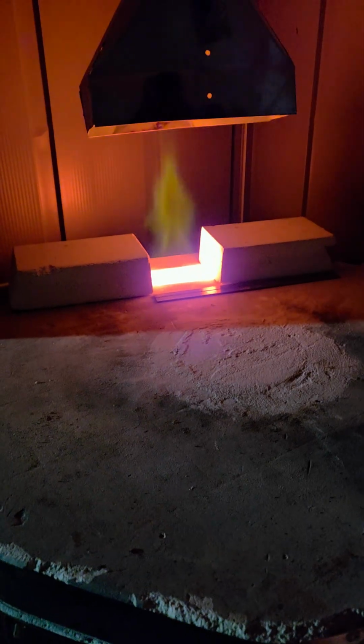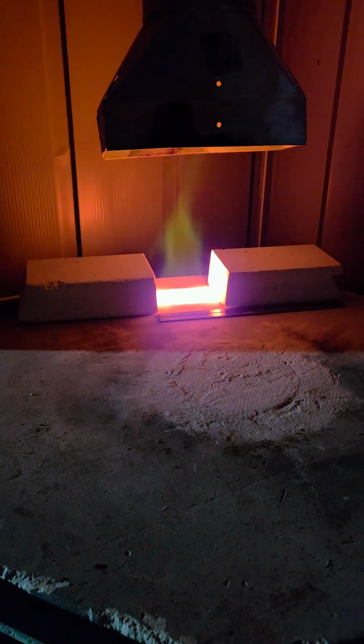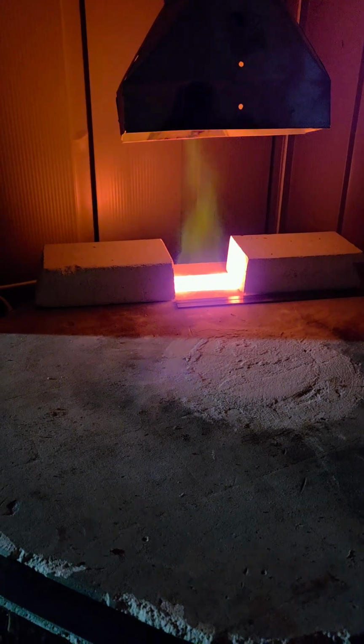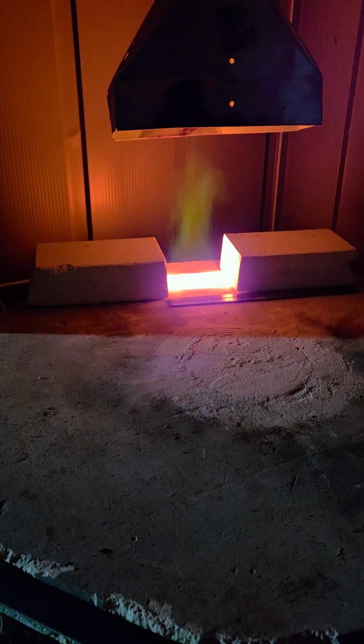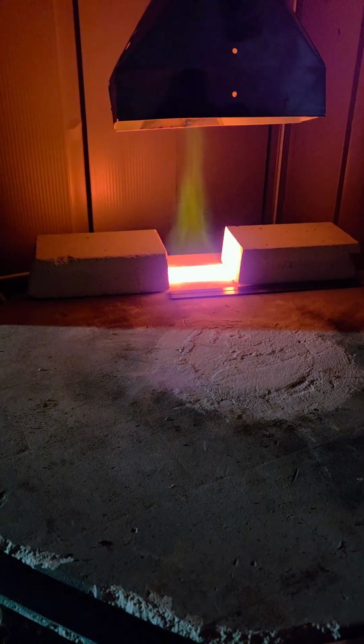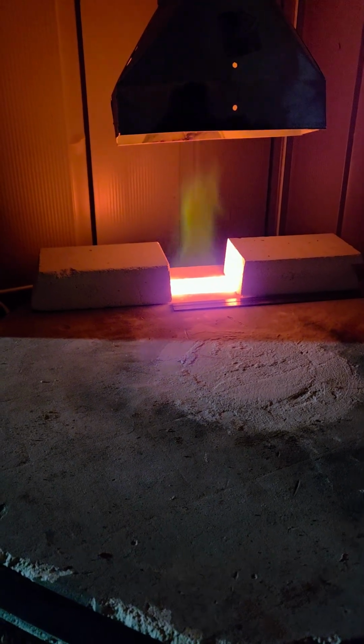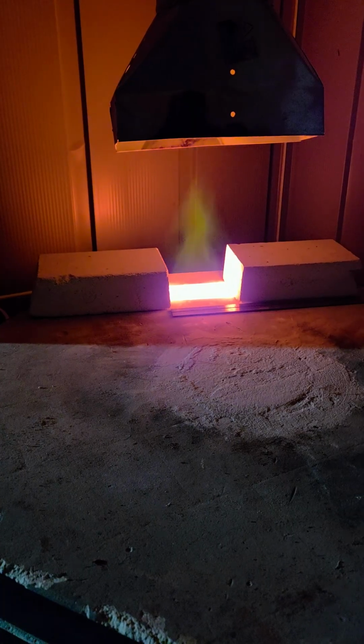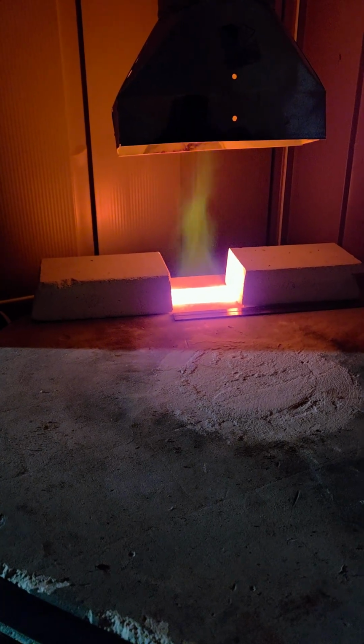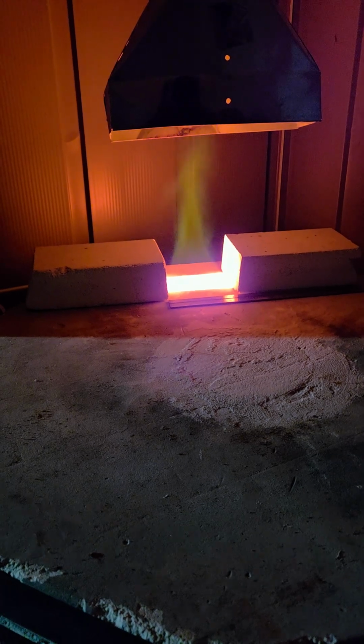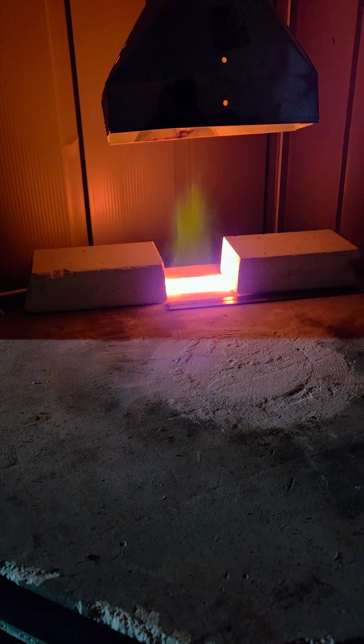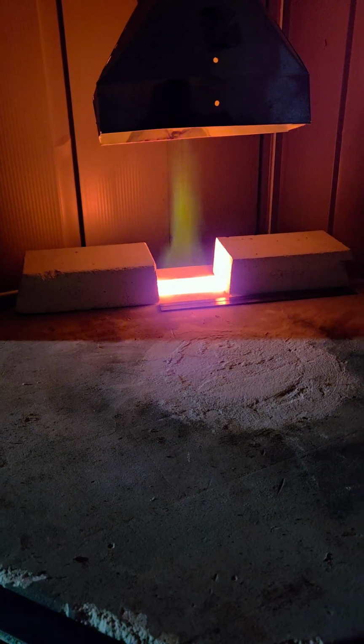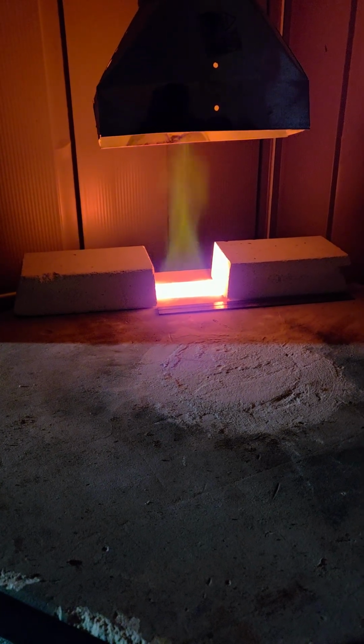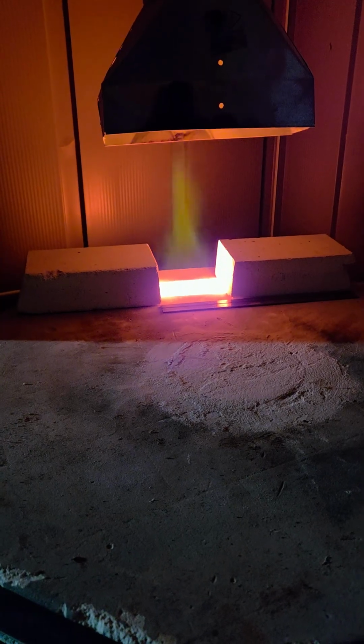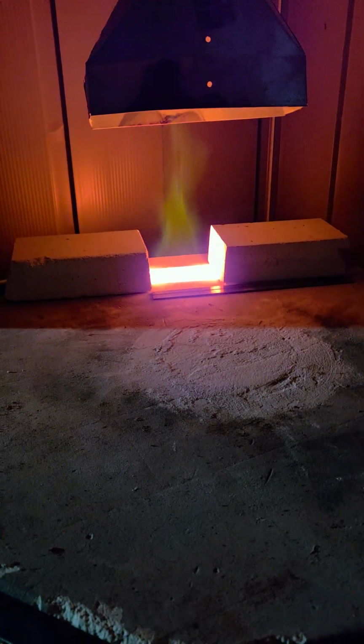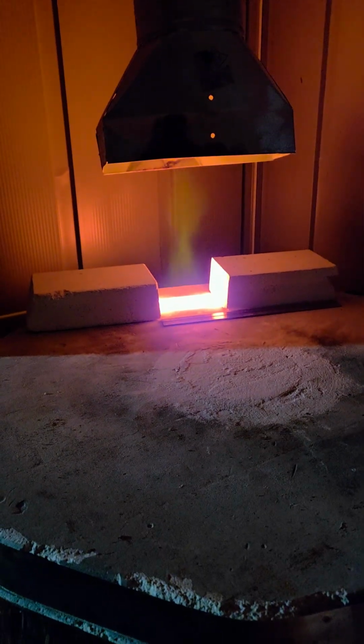I did another time check, and at a temperature of 1236, it's reading about a 60 degree climb per hour. And I checked the cones, and cone 9 is about 3 o'clock, so about halfway down. So it looks like everything's on schedule, although it's happening a little fast, so I'm not going to make any more adjustments, and the firing should slow a bit over the next 30 or 40 degrees. So I'm nearing the end of the firing now.